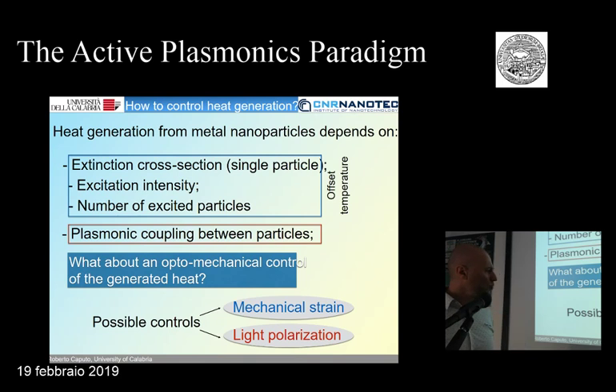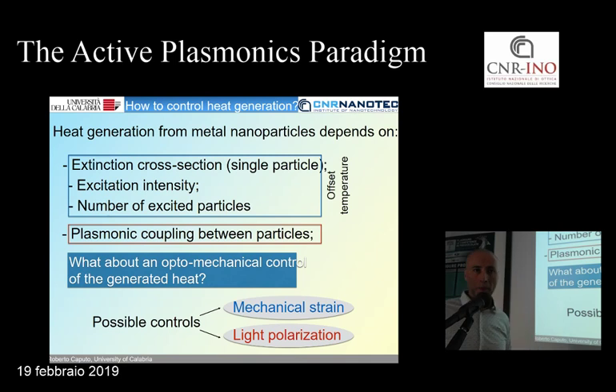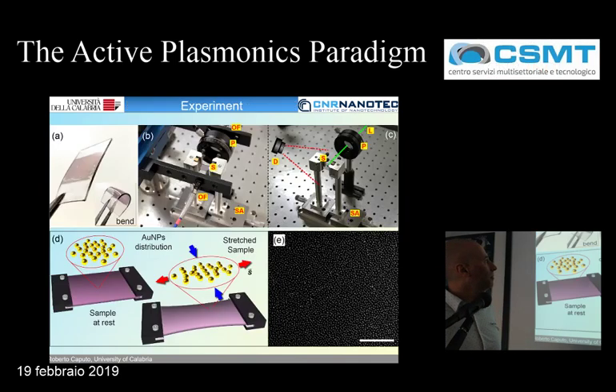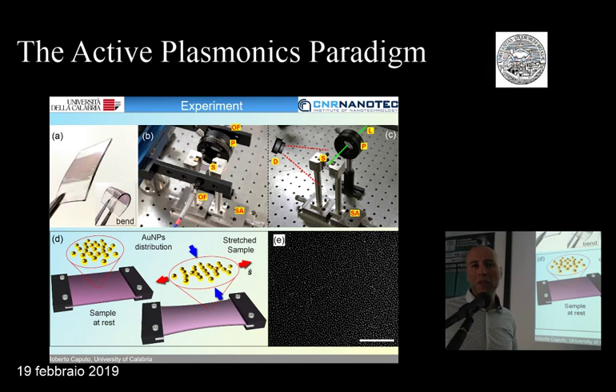And we can see in the following that there are two possible controls. There is a mechanical strain control or a light polarization control. Let's see this in detail. So this is the experiment we performed. As you can see, this is not a very refined setup, but it worked quite well. We just clamped our sample at its extremities, and then we applied the mechanical strain with some precision translators.